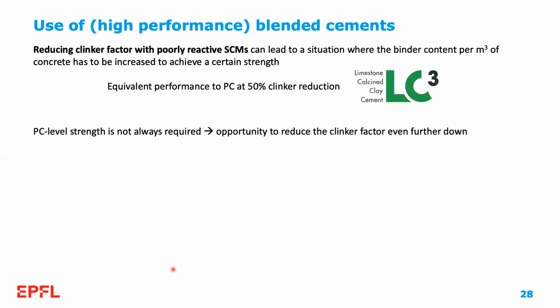Reducing the clinker factor with poorly reactive SCMs can lead to a situation where the binder content per cubic meter of concrete has to increase to achieve a certain strength. This is basically reducing the water to cement ratio, and since we have a water demand for slump, we will have to increase the amount of cementitious materials, and we can end up actually with a concrete that has a higher embodied CO2 content compared to our base scenario.